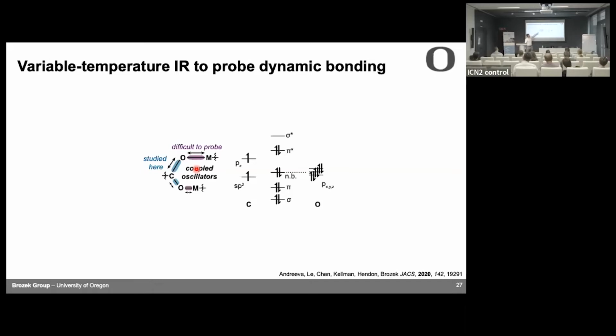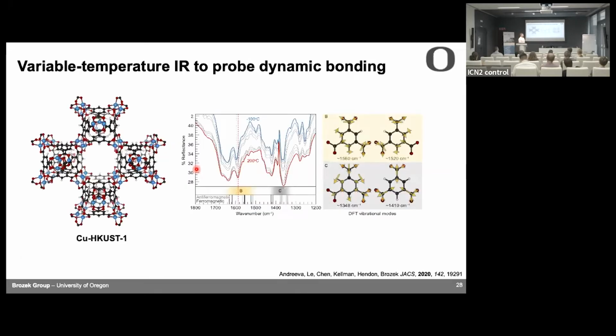So what that means is the more you can get that lone pair to stick onto the metal, the more you're getting these electrons out of these anti-bonding orbitals. And that means that the CO bond gets stronger. So a stronger metal oxygen bond means a stronger CO bond. Alternatively, a weaker MO bond means a weaker CO bond. So the hypothesis was you heat up a MOF, and the CO bond should redshift. That's the simple way of saying what I just said. So that was the hypothesis. And so that's what we did.